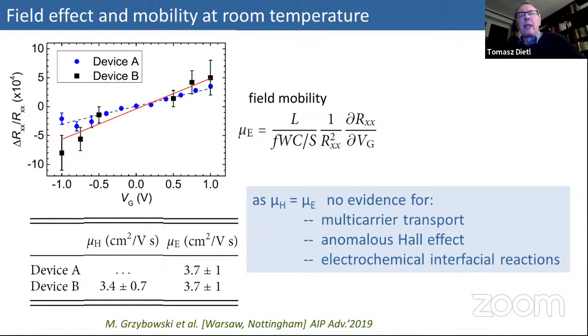I want to say that this crystal Hall effect is very nice, because it shows that orbital magnetization counts, not spin magnetization, but orbital magnetization is determining anomalous Hall effect. And this is a beautiful example for that. Yeah. But you're right, of course. But I said a priori, let's say that we do not know anything, and we just worry that our Hall effect measurements can be affected by anomalous Hall effect. Right. And then field effect can tell us to what extent. Okay, I understand the point now.